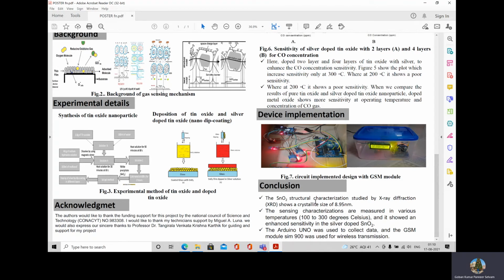Finally, I conclude that the tin oxide structure is formed successfully, and the crystalline size is 8.95 nanometer. The sensing characterization was measured at various temperatures, 100 to 300 degrees, and shows enhanced selectivity and sensitivity in silver doped tin oxide. And Arduino Uno was used to collect the data, and the GSM module was also used for wireless transmission.